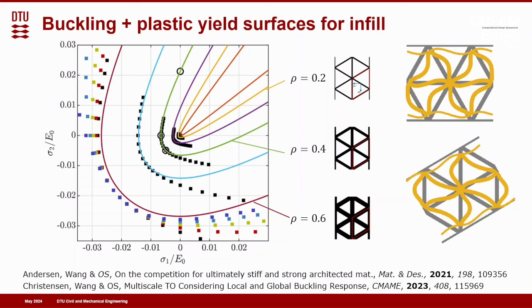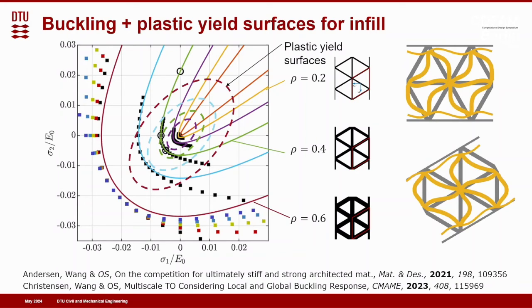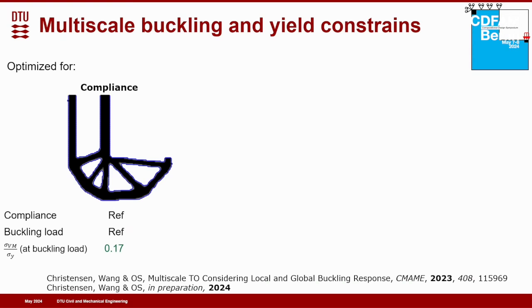So from that, you can generate a buckling yield surface, as I've indicated here, for different volume fractions of the triangular microstructure. But that's not enough, because the structure can fail by local buckling, but it could also fail by local plastic yielding. So you have to, on top of that, also compute the plastic yield surfaces here. So it becomes extremely expensive. So far, we have only done it in 2D, but we want to go to 3D. But I will just show you a little 2D example again to make you think about latticing again.